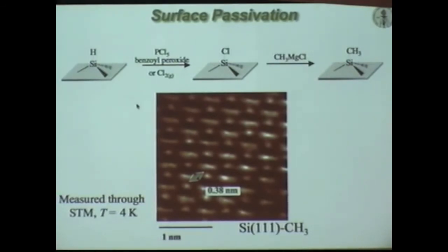So we prevent that. We'd already done that on single crystals by making a metastable surface, a chlorine-terminated surface, and then treating it with a Grignard or a methyl lithium reagent to make a silicon-carbon bond. The important thing about doing this two-step process is we can add methyl as well as ethyl, and methyl's the only group that can sterically terminate every silicon site on a 1-1-1 unreconstructed silicon surface. These have very low surface recombination velocities, less than 10 centimeters per second. They're stable in air for months. And so we can mitigate against that higher surface area because we're chemists.